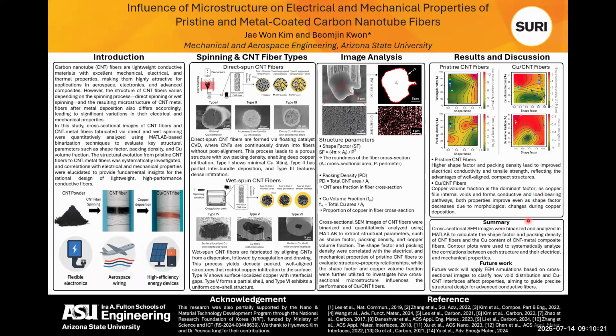In conclusion, this study demonstrates that the internal structure of CNT and copper CNT composite fibers has an impact on their electrical and mechanical performance. By analyzing cross-section images using MATLAB, we quantified shape factor, packing density, and copper volume fraction, and visualized their correlation with performance. In future work, we plan to conduct FEM simulation based on real cross-section images to better understand how void distribution and copper CNT interface influence charge transfer and load transfer.